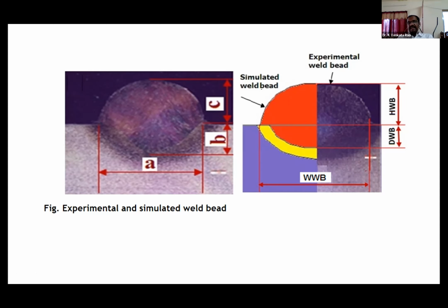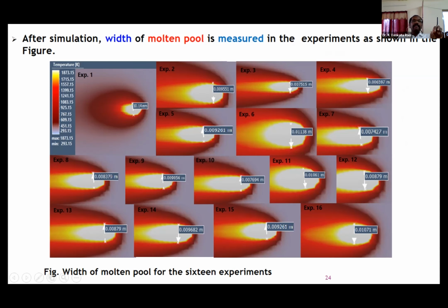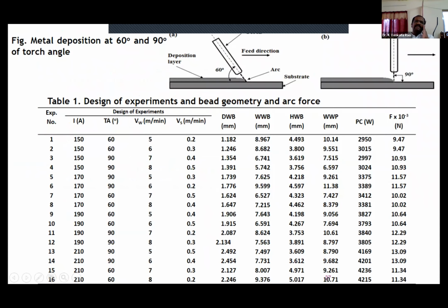So in this present study, what we did, effect of arc force, not only arc force. In this experiment, we conducted 16 experiments taking 4 input parameters. Current is 1 input parameter: 150, 170, 190, 210. Torch angle we took only 2 levels, 60 and 90. This is welding speed 5, 6, 7, 8.